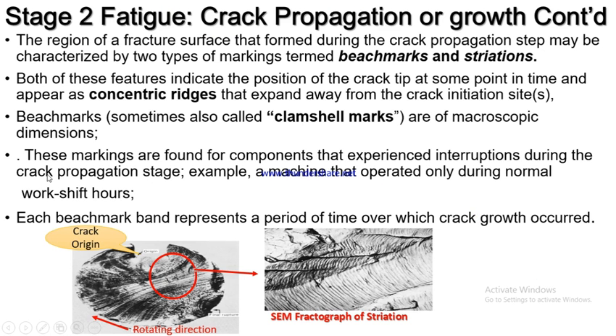Then stage 2 continues. So let's talk about this beach mark. Like I said, the region of the fracture surface that formed during the crack propagation step may be characterized by two types of marks, which are called beach marks or striations. So when you look at the surface of a material fractured under fatigue, you can see the ridges. These ridges are called beach marks, especially when you can see them with your naked eyes and don't need any aid to look at them. We say it's a beach mark. This is it. It's a beach mark.